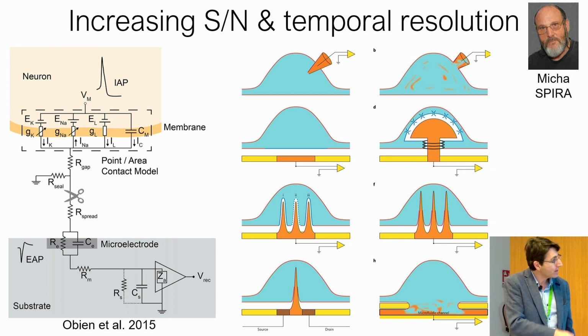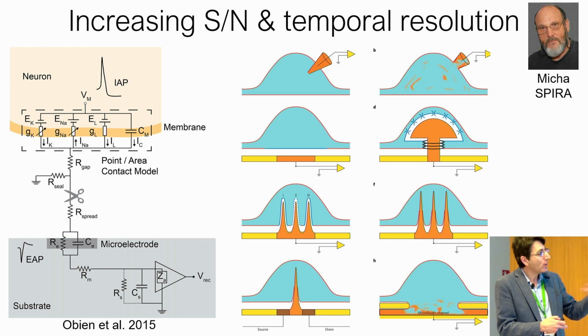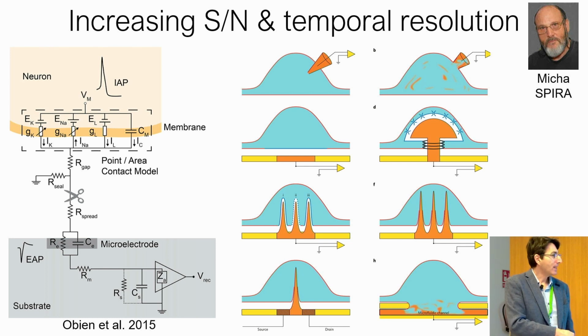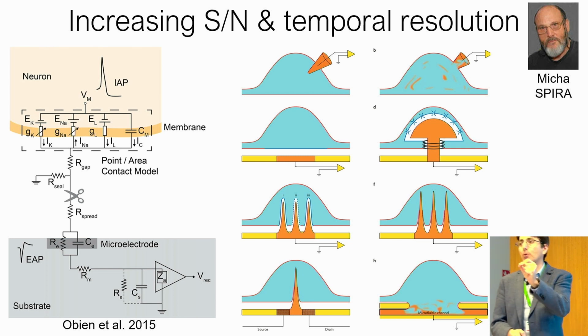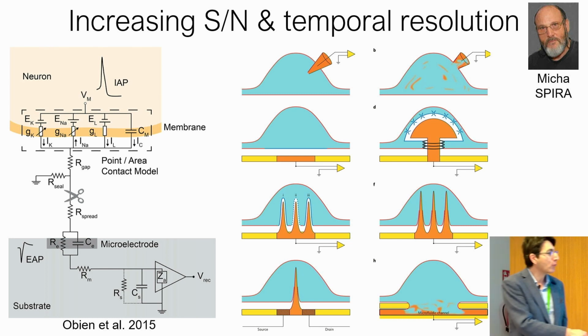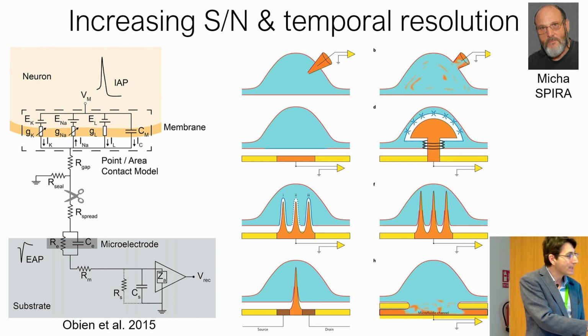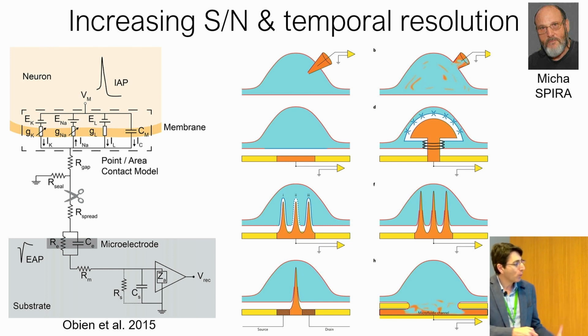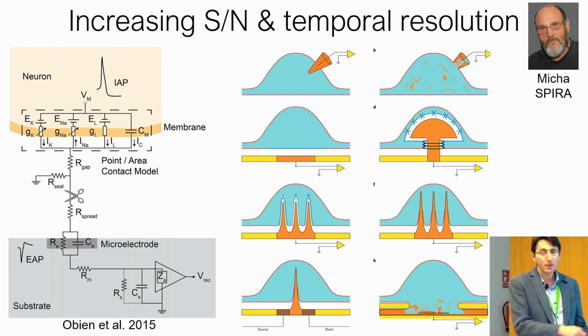And of course, here is the intracellular access, but this makes it possible to record also synaptic activity. And here, this is a picture from a review from another pioneer in the field, Micha Spira, with whom we had a project that I coordinated. And he actually envisioned a different approach in which you may not have an extracellular electrode, or maybe you do have an extracellular electrode that has some sort of three-dimensional feature. And maybe instead of passing very small current to burn the membrane, to electroporate the membrane, to cause holes in the membrane, like in this case where these, say, silicon nanowires are penetrating the membrane and indeed getting a continuity between intracellular and the electrode itself, he envisioned a way in which the neuronal membrane could engulf, could eat, could swallow an electrode just by itself. And this embrace, this engulfment, could be so tight that the input resistance could go very high.